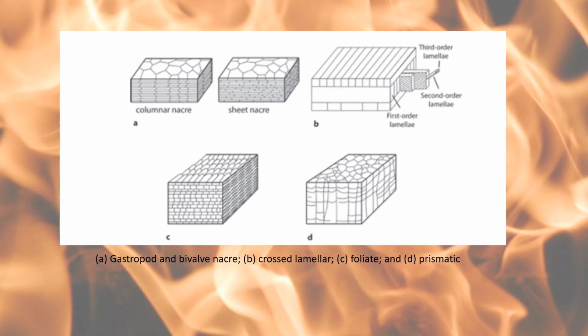For shell, however, the research is incredibly patchy. While mineralogical transformations are acknowledged, shell is made from calcium carbonate in one of either two forms, aragonite or calcite, and aragonite is the less stable form, and over time and with particular contextual cues, aragonite will transform or recrystallize to calcite. One of the major catalysts for this transformation is high temperature and thus burning. And this transformation is well acknowledged in the literature, although the mechanics are patchily understood.